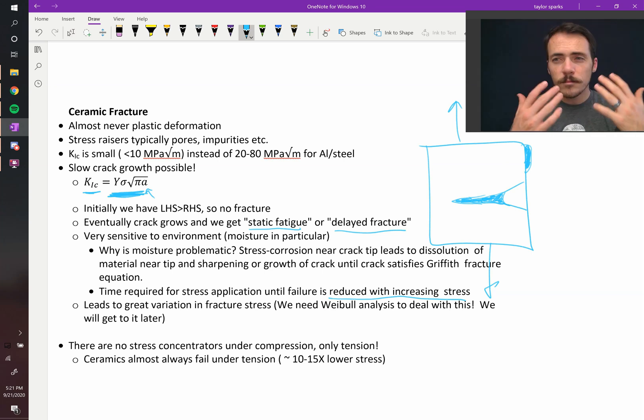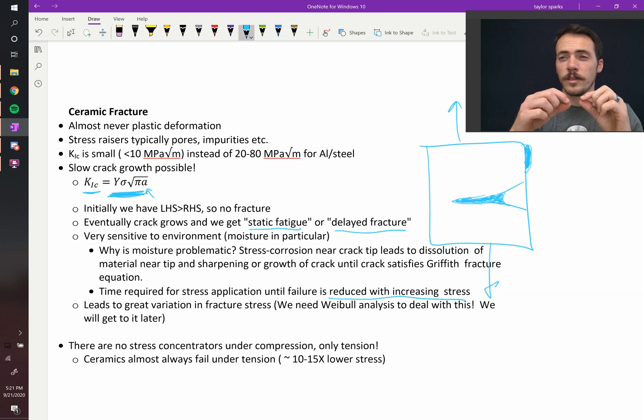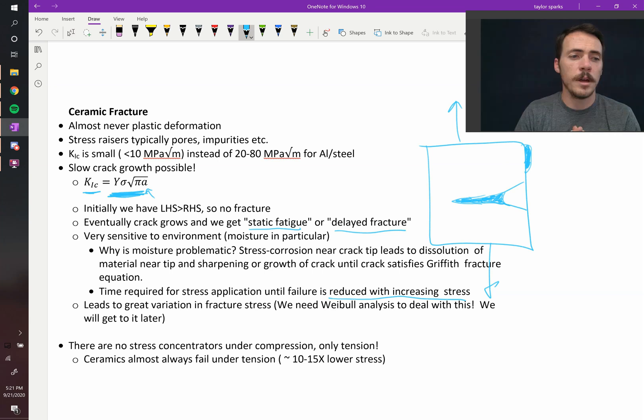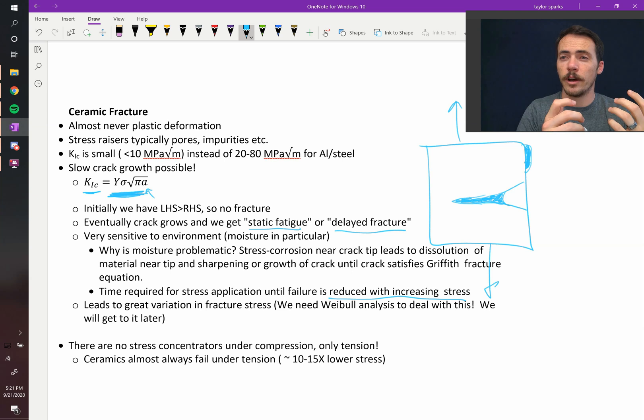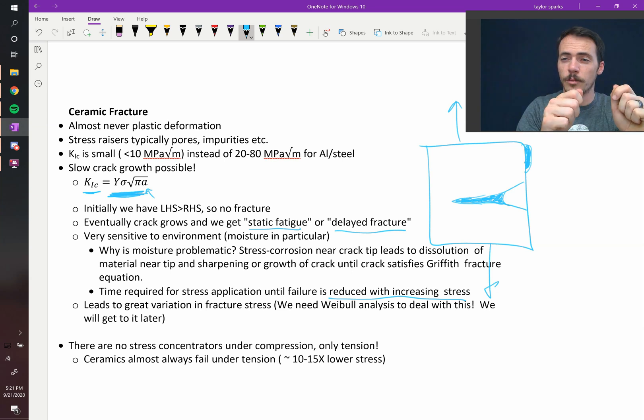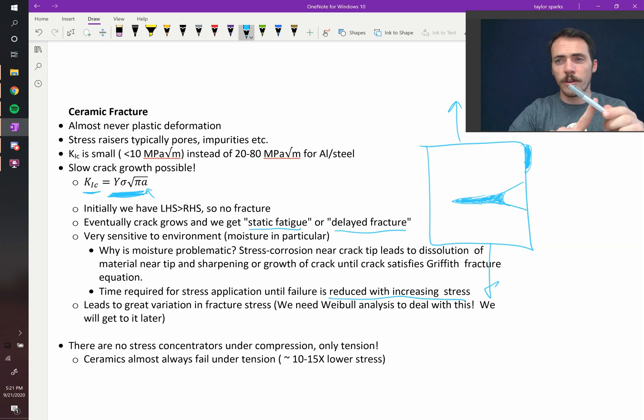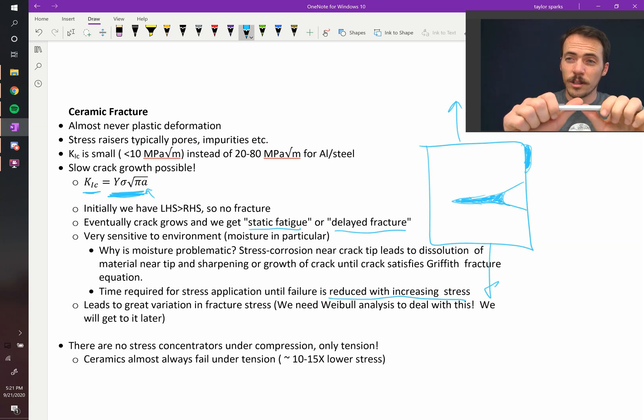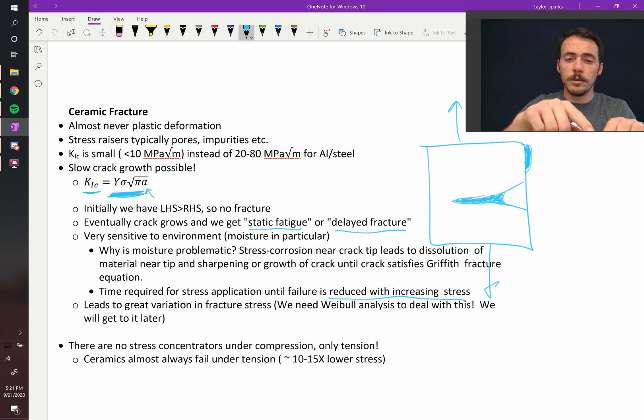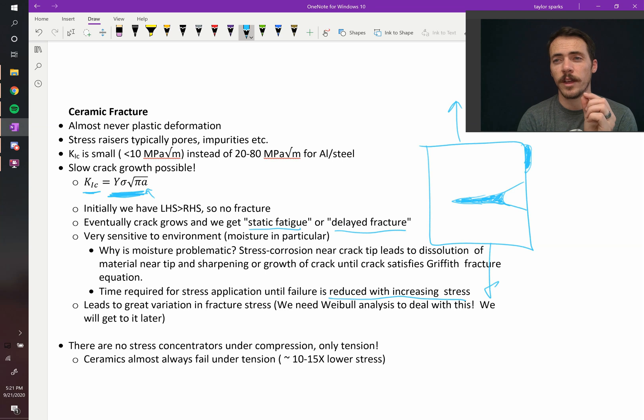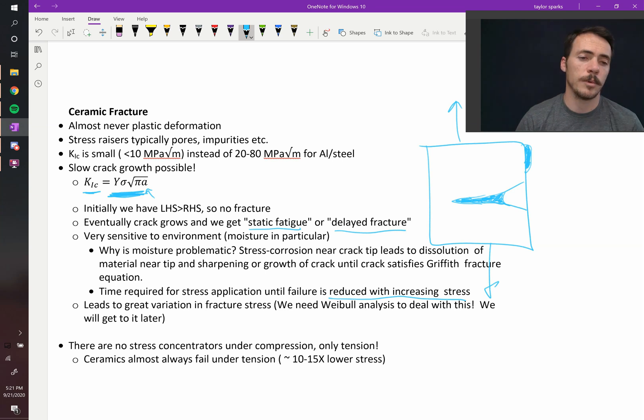And you can see this. My advisor, when I was doing my PhD, we had to break these quartz tubes regularly to seal samples inside of them, and so you scribe them to put a surface crack on it. The surface crack now is a flaw, so you know that it's going to break along that surface crack. That lets you break it in a nice way. But then he would lick his finger and wipe it along the crack, and when I'd be struggling to break some of these tubes, because quartz is pretty tough, all of a sudden he would do that, and then I could take it, and I could pop it right in half pretty easily, because just that easily, by putting that liquid at the surface of the crack, greatly weakened it. So that's an example of that.